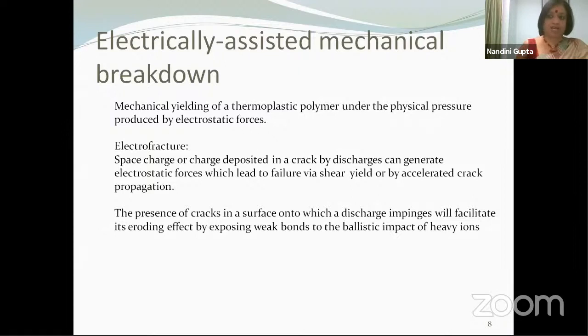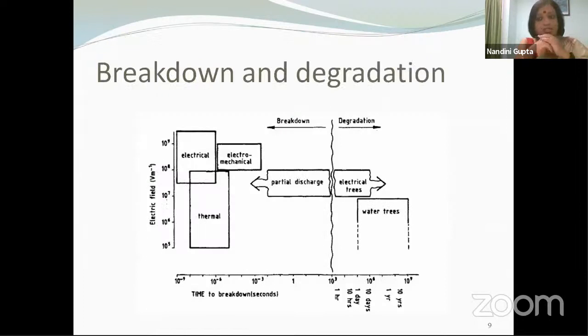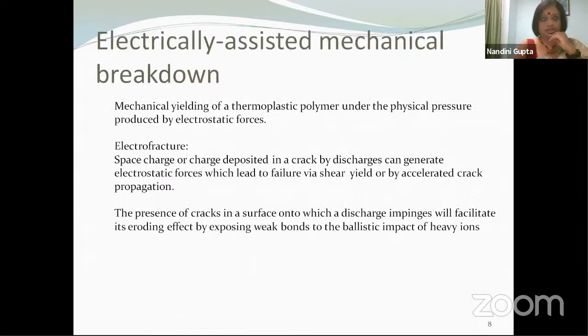We have also seen that before electrical breakdown can happen, the thin film can actually break mechanically. In fact, we have worked with elastomers. Elastomers can be used for energy storage devices. We have worked with elastomers, and we have seen how just by applying electrostatic forces across a thin film of an elastomer, it is possible to make the elastomer completely break down mechanically. It will absolutely tear.